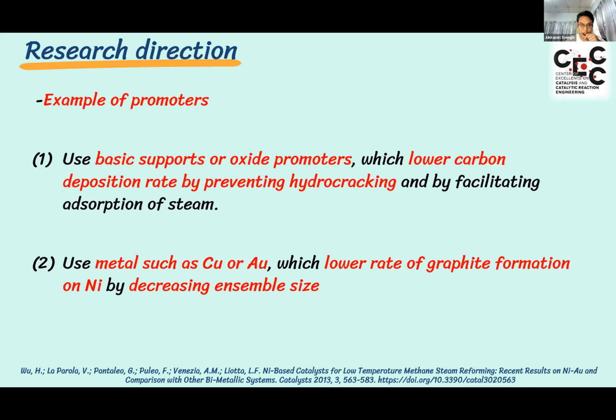First is to use basic or oxide promoters, which lower the carbon deposition rate by preventing hydrocracking and by facilitating adsorption of steam. Second is to use metals such as copper or gold, which lower the rate of graphite formation on nickel by decreasing ensemble size, since carbon formation on metals requires a critical ensemble of surface metal atoms.